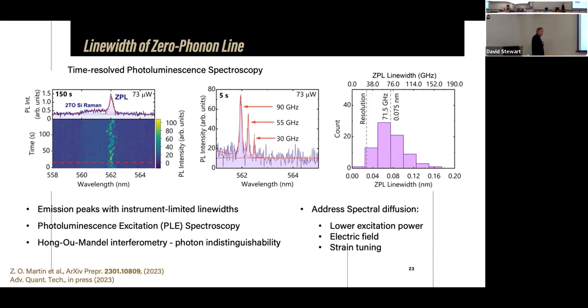And what is required for that, a simple equation probably tells you. So the photon should be emitted with a rate higher than the rate of decoherence. Then all single photons would be identical and indistinguishable. And the thing to mention right away, what we're actually trying to beat: the typical rate of spontaneous emission is around a nanosecond, whereas the typical rate of decoherence, basically when phase is randomly changed, is around a picosecond or less.